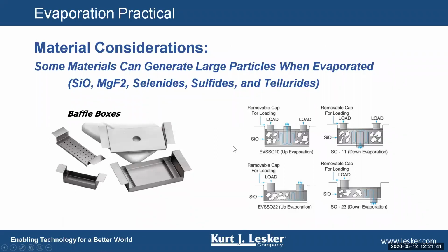Some materials, when they evaporate, generate large particles, and you'll see this commonly with silicon monoxide, mag fluoride, most selenides, sulfides, and tellurides. And they have special boats to do these materials in if you're trying to evaporate them. The idea here is that if we make the vapor stream change directions on its way out of the source, generally we'll filter those macroparticles out and we'll get relatively pure vapor going to the substrate, and you will get a good coating on the substrate, hopefully with very few macroparticles.